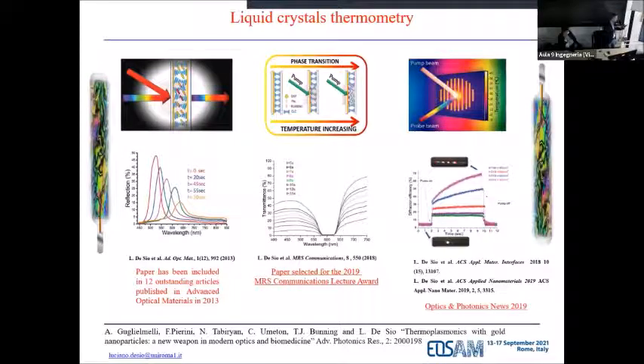In the first experiment, I'm just showing the combination of cholesteric liquid crystals. Those liquid crystals are like springs essentially, and gold nanorods. When you activate those gold nanoparticles, you can do two things. You can measure first off the temperature increase nearby the particles. You can change the elongation of cholesteric liquid crystal, thus making a kind of tunable Bragg mirror. Another compelling application was a bit different in a kind of layer by layer geometry, where we cover spherical gold nanoparticles again one more time with cholesteric liquid crystals.